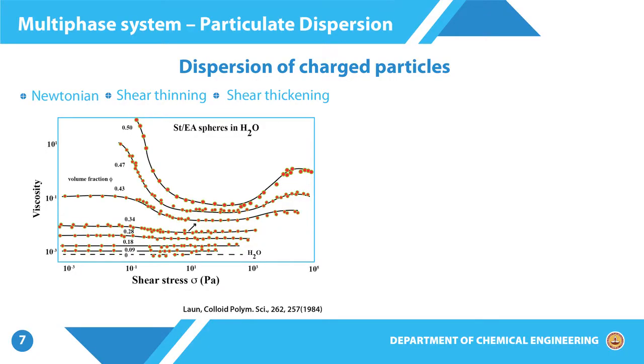And so, this naturally leads to a decrease in viscosity, and we can see that over a small half an order of magnitude change in stress, the viscosity undergoes almost 2 to 3 orders of magnitude change.